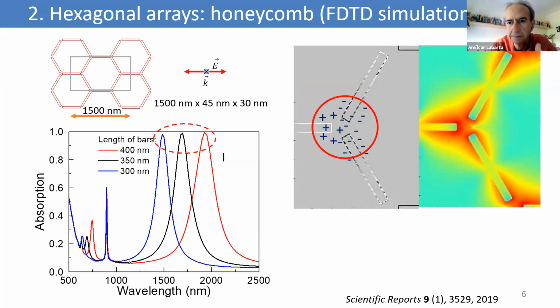to what happens in a spin ice, no? You know, in a spin ice, the spins that are converging in a point can have only 2 polarities, and there is an odd number of spins converging in this point, so you have always a different number of spin up and spin down converging in the point, and this is important to determine the properties of the spin ice. So this is something equivalent here, and if you look at the electric field distribution, you can see that it's not a twofold distribution, so it's not what you can expect for a simple dipolar excitation.